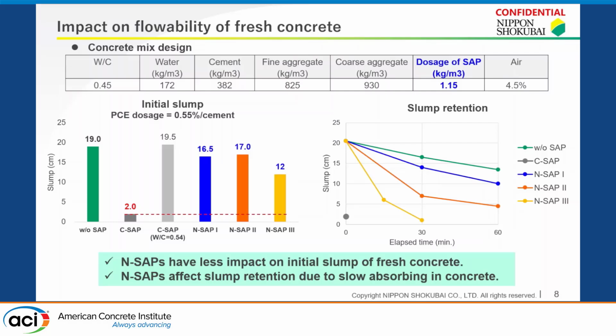This graph clearly indicates that while conventional SAP affects flowability significantly in initial slump, the decrease in slump was much less when using new SAPs. And this data shows the effectiveness of our new design for superabsorbing behavior, and minimizes the negative impact on flowability.